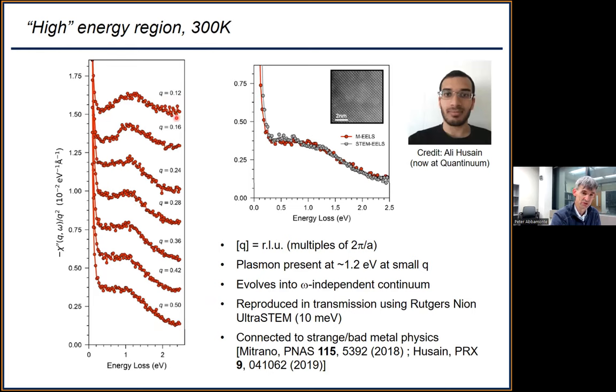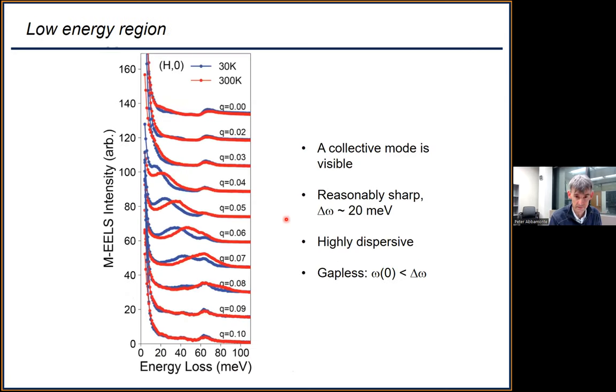At any rate, at the smallest Q, what you see is a peak. And it's not exactly 1.5 eV. It's maybe a little bit lower. And it's really broad. Nevertheless, that's the plasmon. Okay, so strontium ruthenate has a plasmon. It's roughly at the energy you expect. It's extremely broad. I mean, the way I always say it, it's not a plasmon that you'd bring home to meet the parents, but it's there. So good. Nice check. So let's now look at low energy and see what we see.